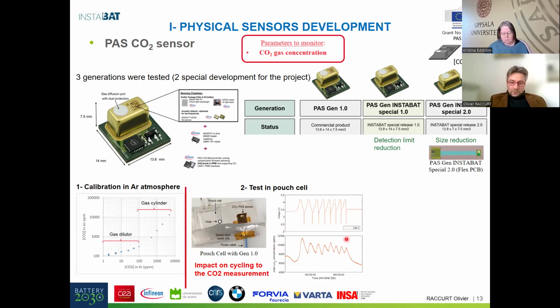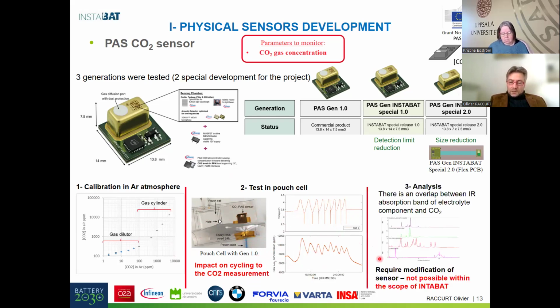And there were a lot of questions after this experiment, and we explored in more detail what happened with the sensor. We identified that the sensor was based on the absorption peak of the gas in the infrared area of the CO2, but this absorption is at the same wavelength as the infrared peaks from the electrolyte components, such as the carbonate. That's why we don't measure the CO2 in this case, but we probably measure other things.